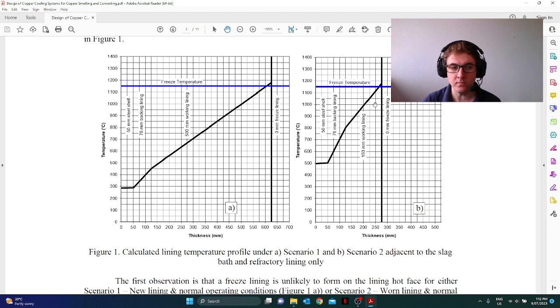You can see here that this solid black line is the hot face, and the blue is your freeze temperature. In this particular system, you have a superheated slag, and you can see that this hot face is just above the freezing temperature. By being above the freezing temperature, the hot face can dissolve slowly in the slag. When you go from this to this, you can still see it's slightly above it, so it just keeps on eating away slowly. You can see that steel shell at 300 to 500, a hot steel plate towards the end of the campaign. People can sometimes get a bit concerned there, but you generally start to re-brick after certain conditions.